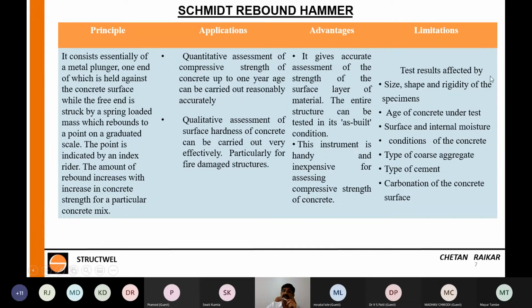Limitations are test results affected by size, shape, and rigidity of the specimen, age of the concrete under test, surface and internal moisture conditions of the concrete. See, if it is moist, the hardness will change, isn't it? So if the concrete is wet, it will surely have a different reading. Then type of coarse aggregate, type of cement.